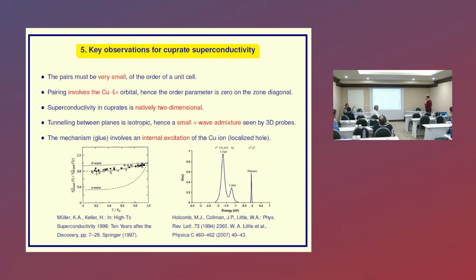It is natively two-dimensional, and now one beautiful side effect of this whole story is that if the pair is very small, then the tunneling between the planes of this pair is point-like, which means isotropic, which means that the order parameter should have a small S admixture coming from this isotropic tunneling. And lo and behold, Alex Müller in 97 and Hugo Keller, they actually nailed it.